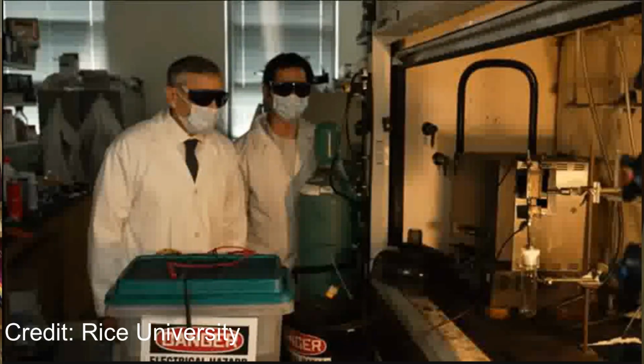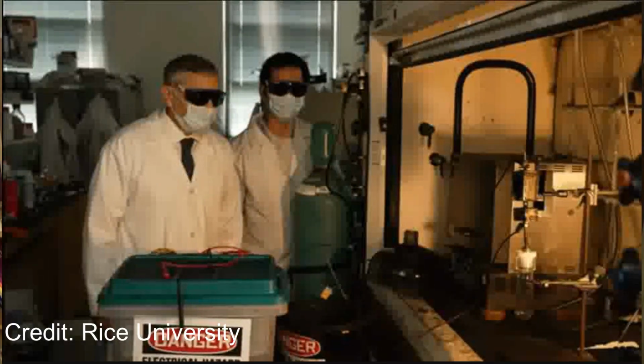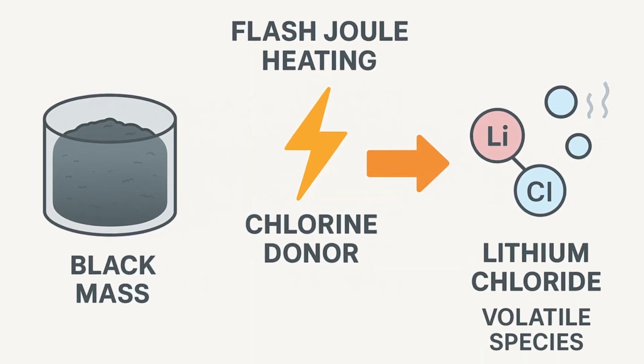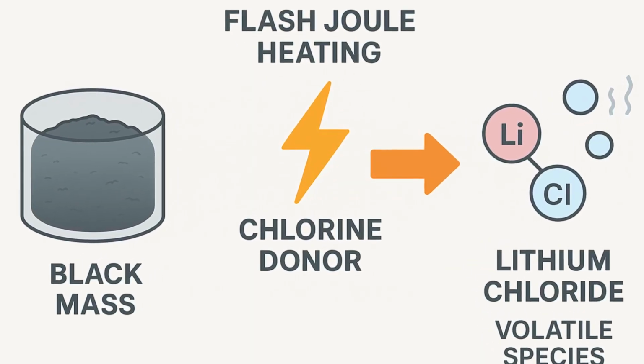Flash Joule heating with chlorination takes about 60 seconds. An intense current pulse heats the black mass. In the presence of chlorine or a chloride donor, lithium forms lithium chloride, and other volatile species can be driven off or transformed. The heating is so fast that elements are selectively converted based on their transport and reaction rates.